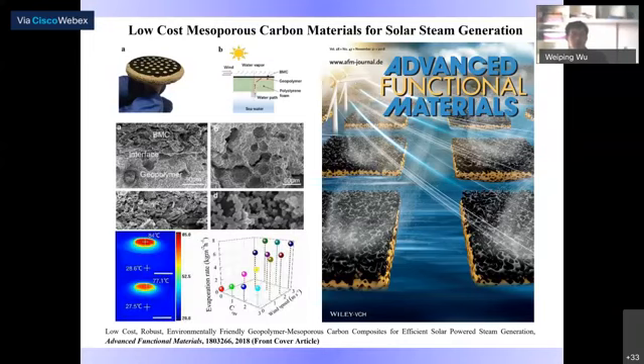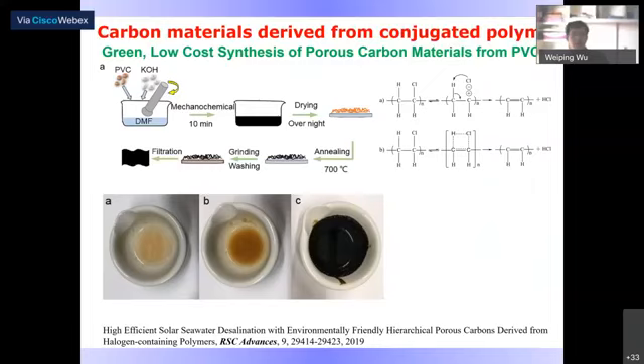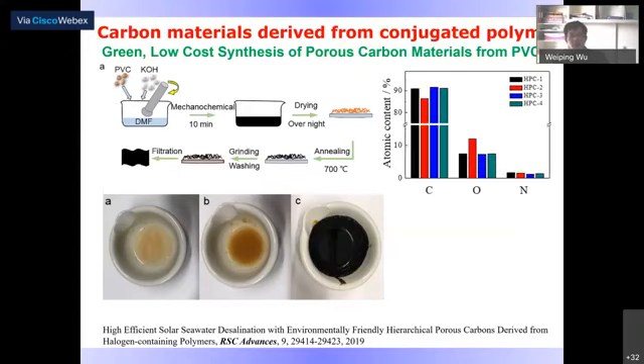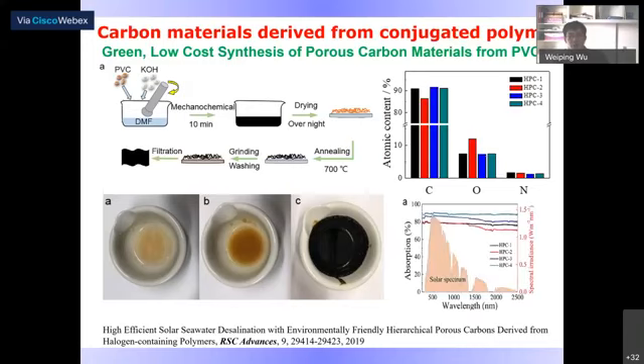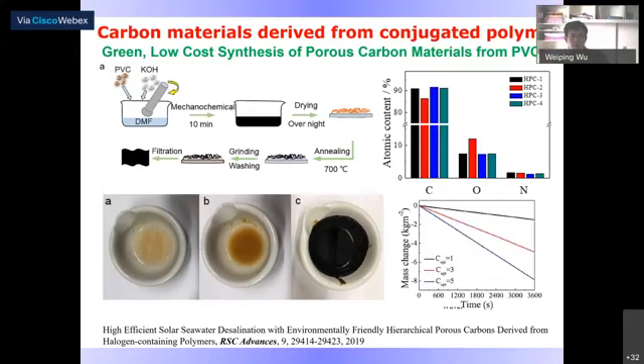Following this work, I further synthesized this carbon material from plastic, particularly PVC, which contains chlorine atoms, for the consideration of reducing pollution and protecting the environment. By a very simple, very low cost KOH treatment, the chlorine can be knocked off and released as HCl or NaCl or KCl in this process, and this carbon material can be obtained at high atomic content, and then got a very ideal solar absorption spectrum. This material showed excellent solar steam generation, as you can see from this figure, especially at concentrated solar energy intensity, like 3 sun and 5 sun. The steam generation rate can be boosted. This is because of the very large pore size that allows efficient mass transfer within these materials.